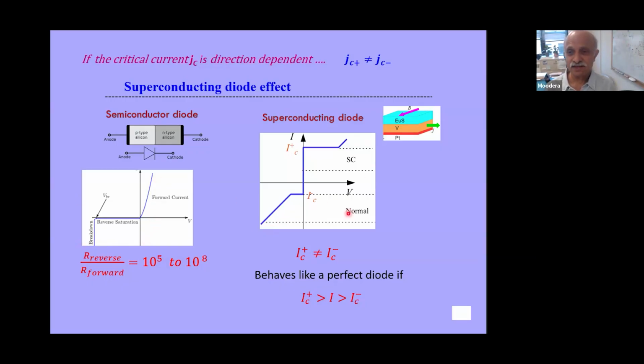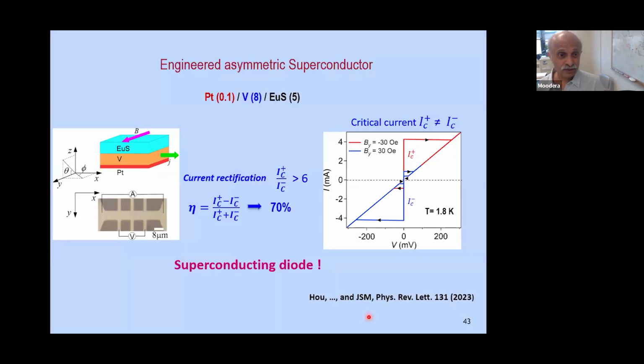If you have a superconductor, let's say the critical current is different in two different directions, then you should have this kind of behavior. In one direction, a very large critical current, in the other direction, a very small critical current. Now, if you are able to maintain a current somewhere in between this point and that point, somewhere here, then on the positive side, you have zero resistance, whereas on the negative side, you have finite resistance. So the ratio of resistance is essentially infinity. Now, this kind of system behaves like a perfect diode. Okay. Now, that's what we see.